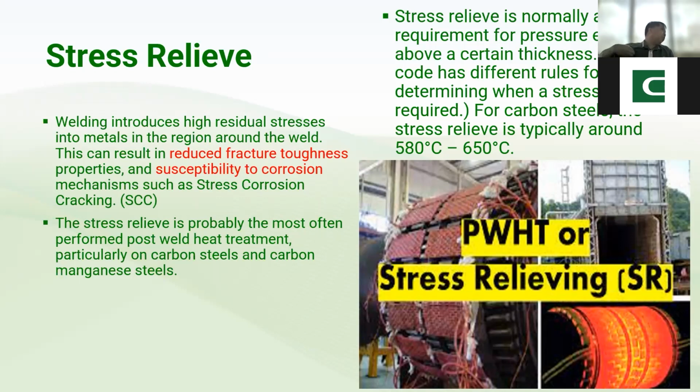Sir, pa-repeat po ng sagot nung sa standard ba yung 1 hour na soaking time. 1 hour soaking time for ordinary carbon steel. But as I mentioned to you this morning, there are high alloying element and low alloying element. For different materials, chrome moly, high alloy steel, 2 hours per inch thick.